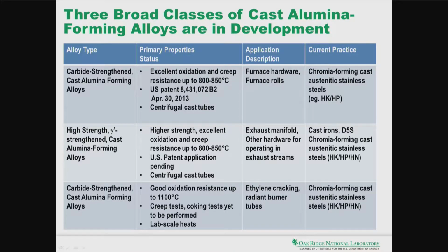The D5S, which is a high nickel version of cast, it's a cast austenitic steel, but it's a cast iron. And of course, many manufacturers are even going towards cast austenitic stainless steels or even rod forms, simply to withstand the higher temperatures and corrosive environments. The third class of alloys that we really are aiming towards the ethylene cracking and radiant burner tube applications, which is where the temperatures are approaching about 1100 C. As I will show you later, we have identified some alloy compositions within the granted US patent that would be able to perform at these temperatures.